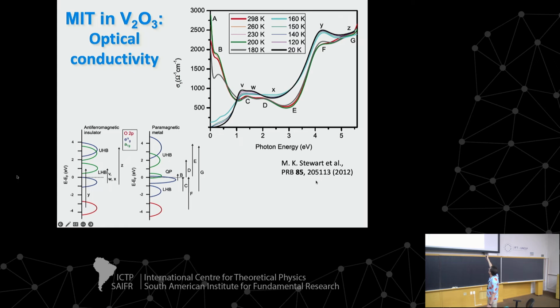And then in the insulating state, there is a gap opening, again, of the order of 500 millielectron volts. And then you have these transitions, which are also from lower to upper Hubbard band or from the valence band to the higher-lying bands. Okay. There were also previous angle-resolved photoemission measurements on this system, but only in the metallic state.